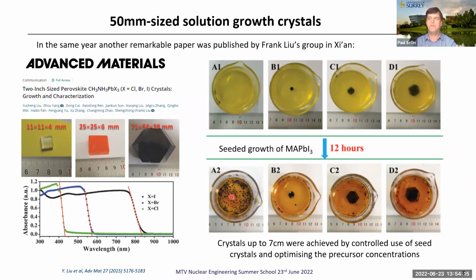If you go for an organic perovskite, then obviously you've got a lot of hydrogen in there, and you'll get proton recoils from a fast neutron. That is certainly an area of active study. People are looking at their sensitivity to fast neutrons from the proton recoil of the organic molecule.